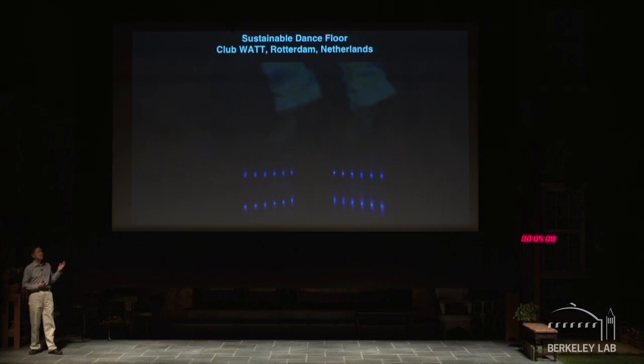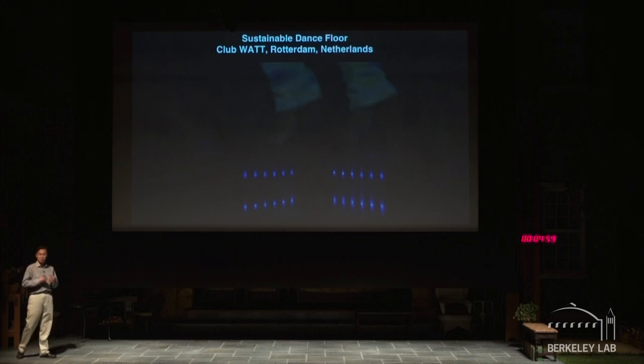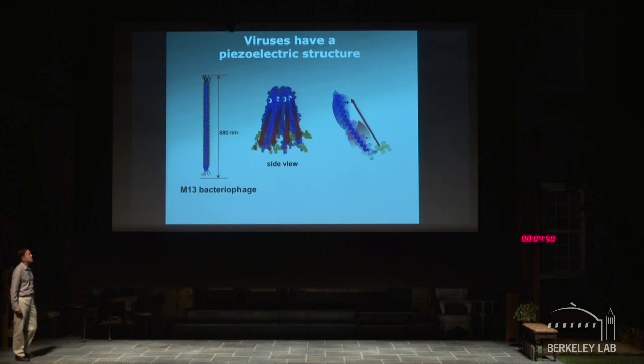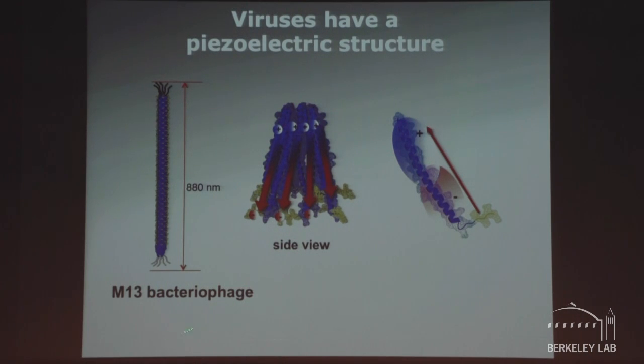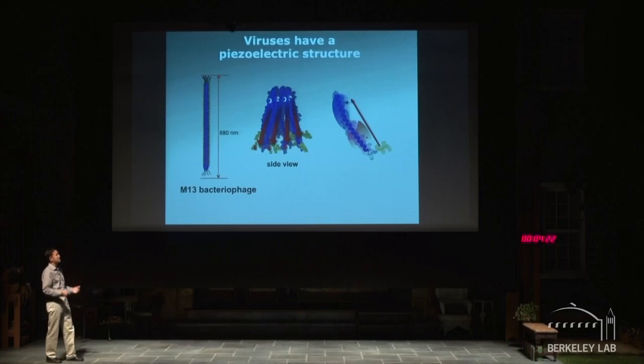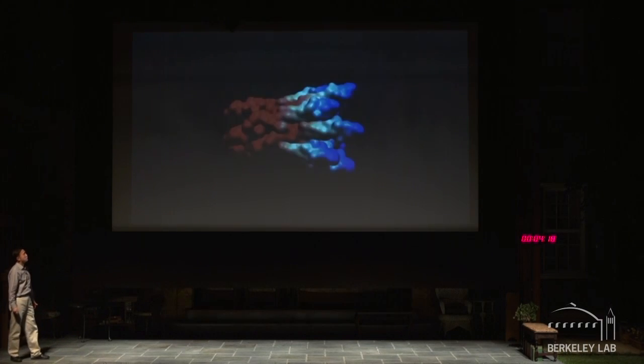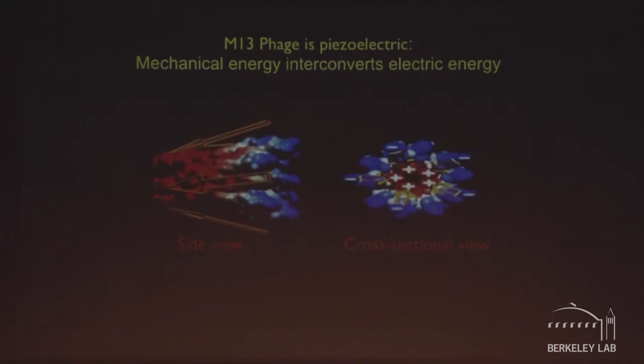The problem is that these materials are very expensive to produce and composed of many harmful chemicals. Fortunately, most biological materials are piezoelectric, such as DNA or protein. The virus we use — called the M13 bacteriophage — also has piezoelectric properties because it contains DNA inside and proteins with charges coiled around its surfaces. The DNA is negatively charged, and this protein evolved to produce positive charge inside and negative charge outside, coiled 3,000 times around these materials.